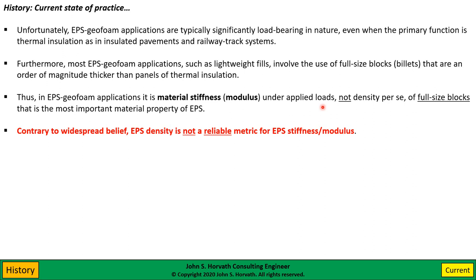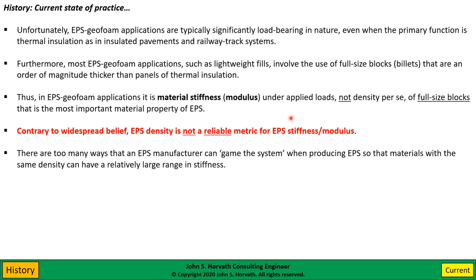There's a lot of ways to game the system. I'm going to go through the manufacturing of EPS in some detail, and you can see there are many steps along the way where you can tinker with the process. In the end, you can wind up with materials that may have the same density but vary all over the place in terms of load bearing. I've seen EPS that has a certain density that'll just break apart in your hand like crumbs. So density has never been a reliable metric for the load-bearing capacity of expanded polystyrene. The geofoam market is a real shift in thinking for EPS manufacturers — it requires a lot more manufacturing detail, focusing on material stiffness, which is something most EPS manufacturers just don't think about.